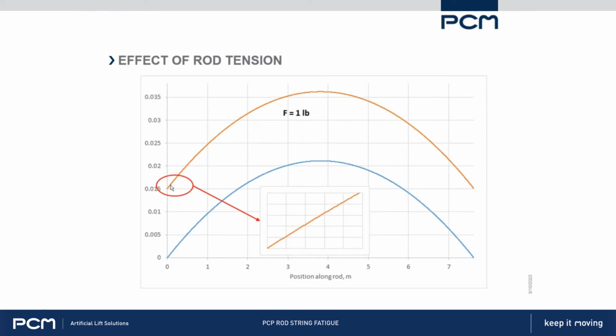And what's happening there is that it's concentrating the curvature. So we're seeing here just the first 50 centimeters or so. You can see it stays parallel on the right at the coupling. The more tension there is in the rods, the more it's concentrating all that curvature in this one spot right near the coupling. So this is why we see fatigue failures at the coupling, and it really affects the things we can do to improve our fatigue life. We want to reduce this concentration of curvature at the coupling.